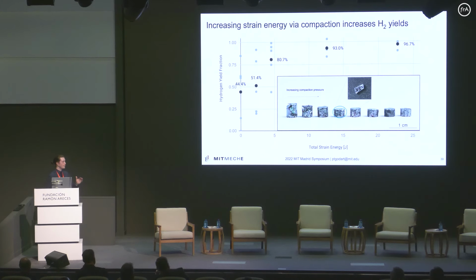But the net result is in the top right corner here. You can see that under the right conditions, we can actually produce fuel that is, one, very consistent in terms of its hydrogen output, but also achieves a very high hydrogen output at almost 97%, which is actually higher than the pure aluminum that we were using before.